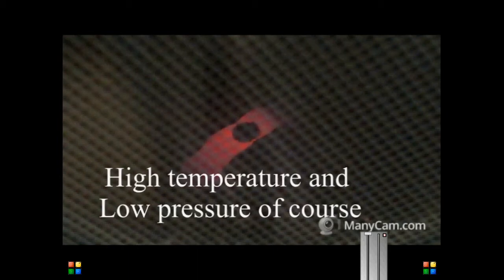It's heating up very quickly apparently, but this took several minutes. I'm running about 60 amps through this small bar of tungsten at a vacuum of about 5 times 10 to the minus 5 millibar. The point of this demonstration is that the reaction appears to go forwards only at room temperature and air pressure, but at high temperature and low pressure it goes in the other direction, driven by the entropy of the released oxygen. The copper oxide is spontaneously reduced to copper just by heating it up in these conditions.